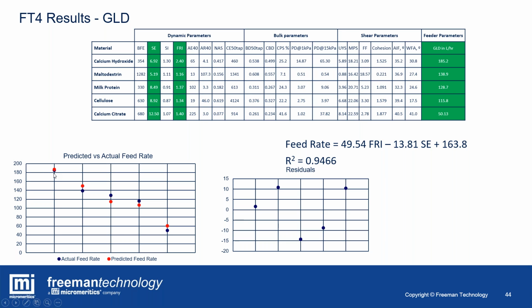You've got the highest volumetric displacement for the calcium hydroxide on the left hand side here, with almost overlapping predicted and actual, right down to the 50 to 60 litres per hour as demonstrated by that calcium citrate. So a pretty robust model.